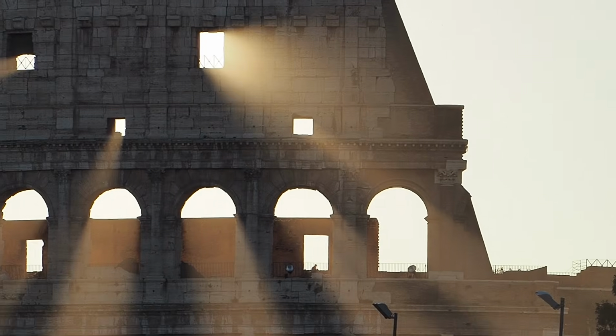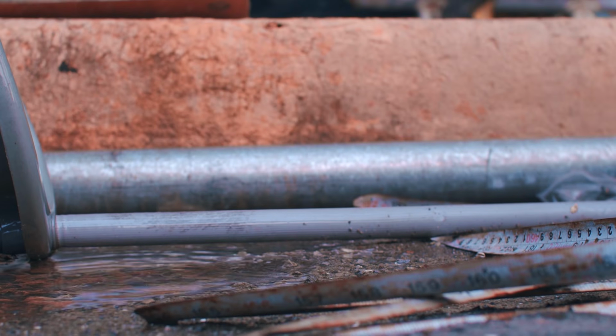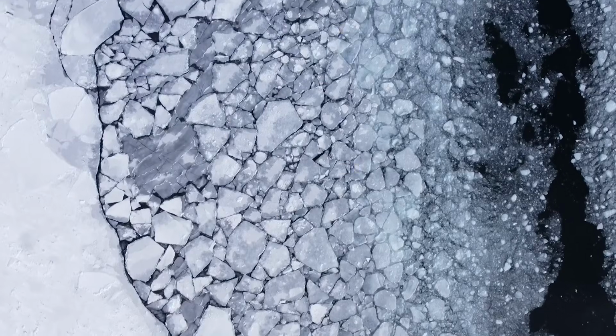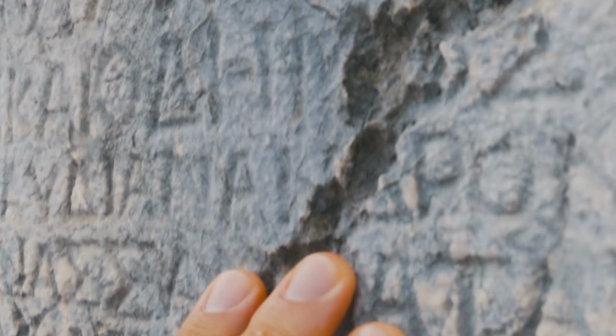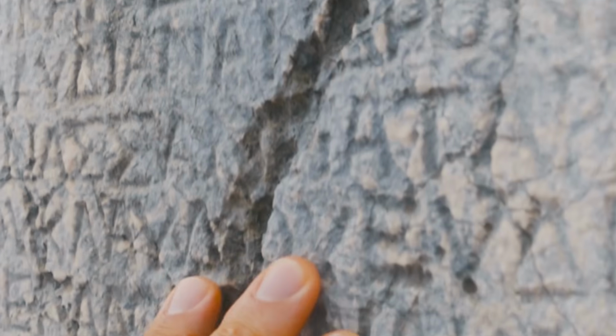They made it self-healing. When cracks form inside the material and water enters, the lime clasts react with the water and dissolve, releasing calcium into the surrounding area. That calcium then recrystallizes as calcium carbonate, essentially forming new rock that fills the crack and seals it.